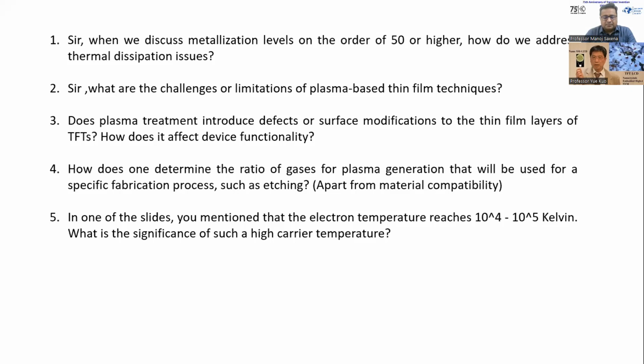When we make a transistor at 250 degrees C, an amorphous silicon transistor, and use silicon nitride, those nitrides are non-stoichiometric. So not Si3N4, actually SiNx with x more than 4/3, slightly nitrogen rich. And the amorphous silicon has high hydrogen concentration. Those films do not exist in nature, but are made by plasma. But those kinds of devices are stable because they are made at 250 degrees C. So we stored the transistor at room temperature for almost 30 years. Today, I took the transistor to remeasure it, and it still works, just like the original. So that's the amazing part of the plasma-based process.